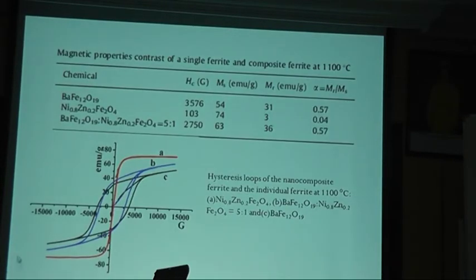Okay, this is the magnetic properties contrast of single ferrites at 1100 degrees Celsius. Actually, they try to sinter at different temperatures in steps of 100, just like the evolution that we are doing now. This is the best that they get from 1100 degrees Celsius. From single barium ferrite, they got a remanence ratio of 0.57 and remanence 31. And from single soft ferrite, nickel zinc, they got only 3.